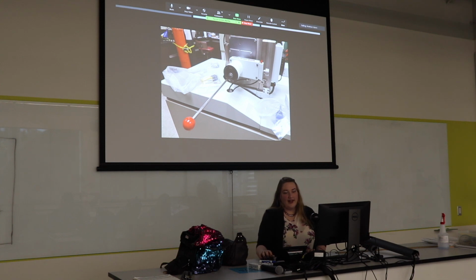Then when the red light turns on, we know that it's ready to go. We pull this knob out, which opens a door inside of here, and then we very slowly and carefully let the pole go in until our sample reaches the stage that's inside of this whole machine. I say slowly and carefully because if you move the arm, the pole at all, you can ruin the vacuum for the entire machine, which has happened a couple times, and you learn very quickly because it takes a very long time to reset the vacuum.